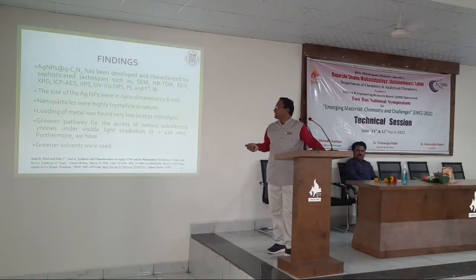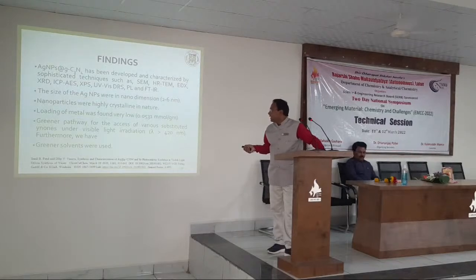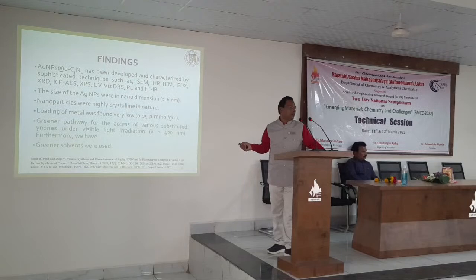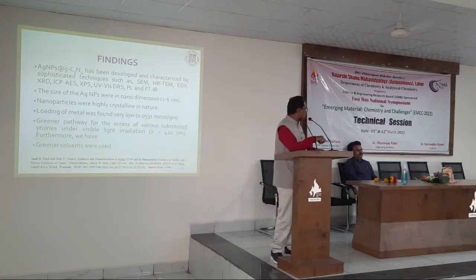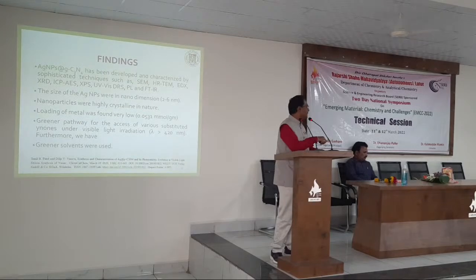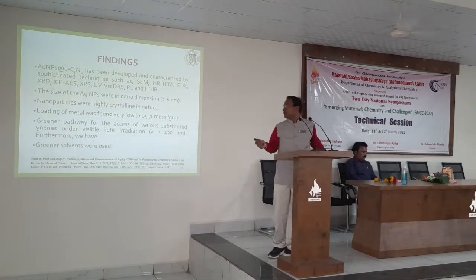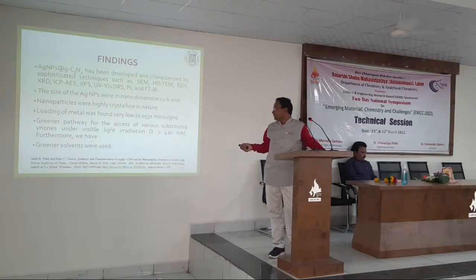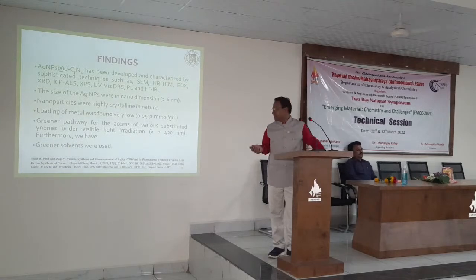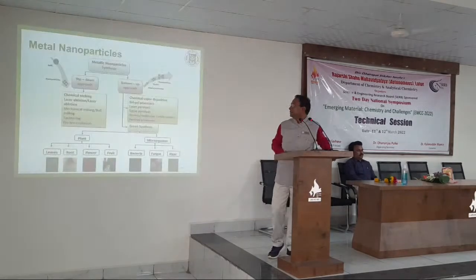So these were the findings. It was characterized by the available techniques, where the size of the Ag nanoparticles was found to be 2 to 6 nanometers, and this was the loading of the nanoparticles. This much was the loading of the nanoparticles, and this is the light source. The 80-watt bulb was taken, with a 420 nanometer wavelength, and the solvent utilized in this reaction.